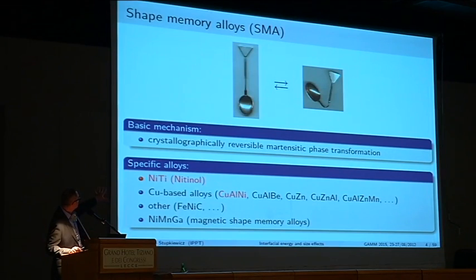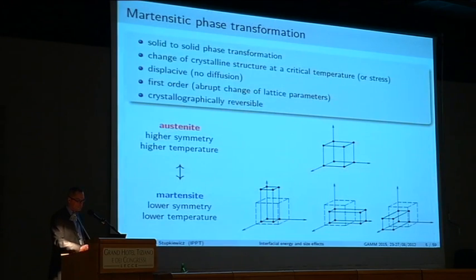What is behind this peculiar behavior is a crystallographically reversible martensitic phase transformation. By saying crystallographically reversible, I mean that the crystallographic structure is not changed. Of course, it's not reversible in a thermodynamic sense, for sure. And there are some specific alloys. The most commercially used is nickel titanium, but there are other ones. We will also use here, as an example, copper aluminum nickel.